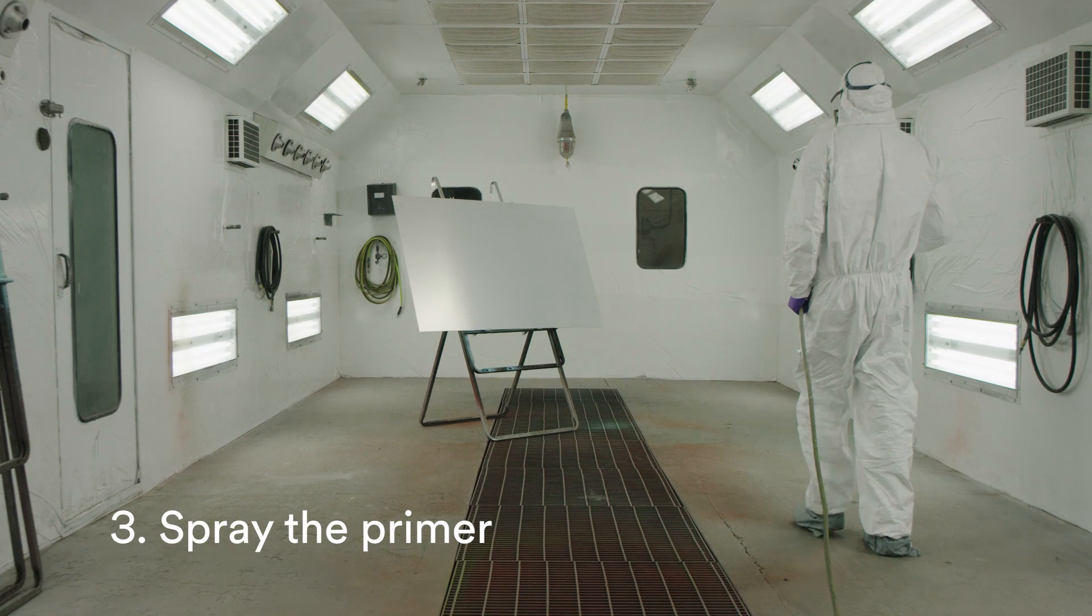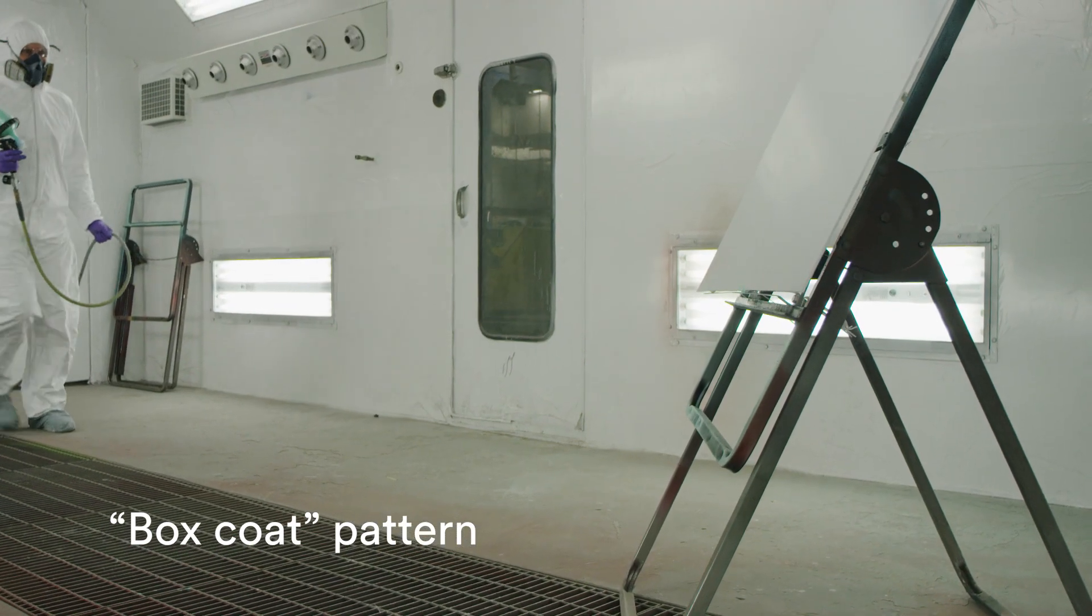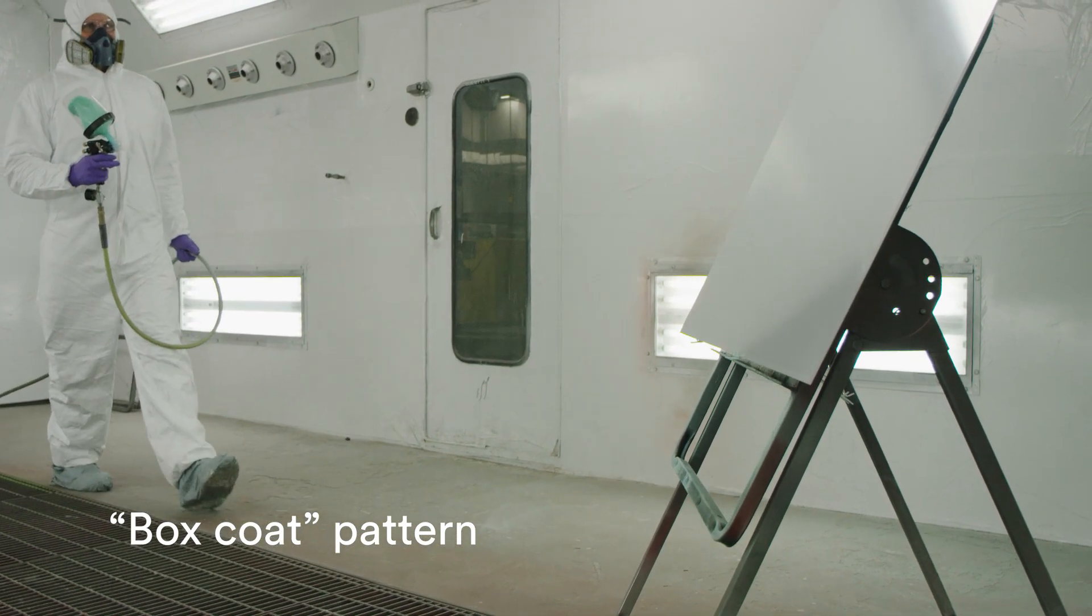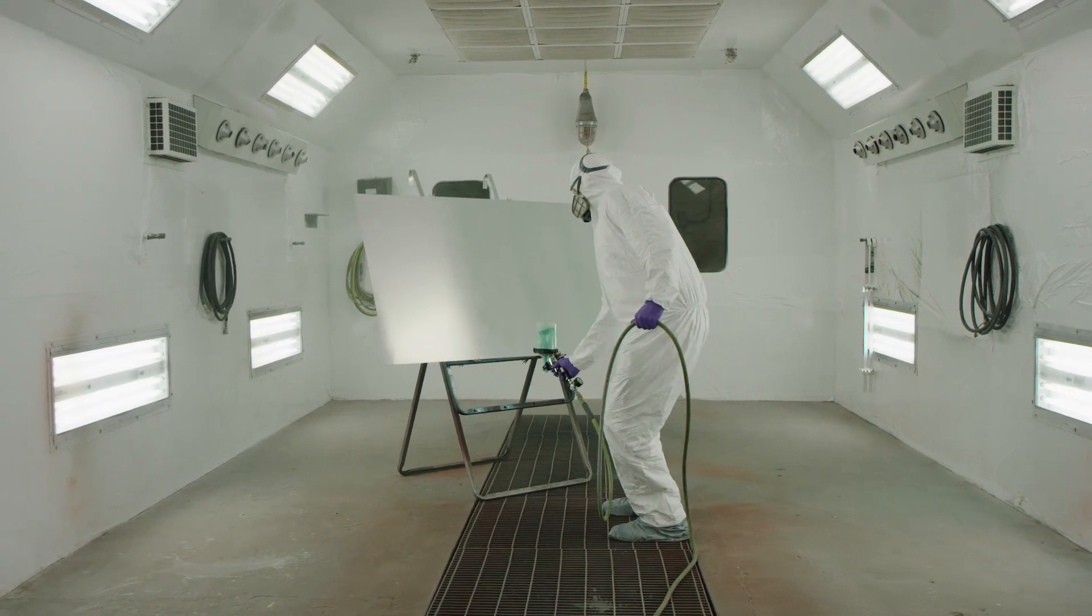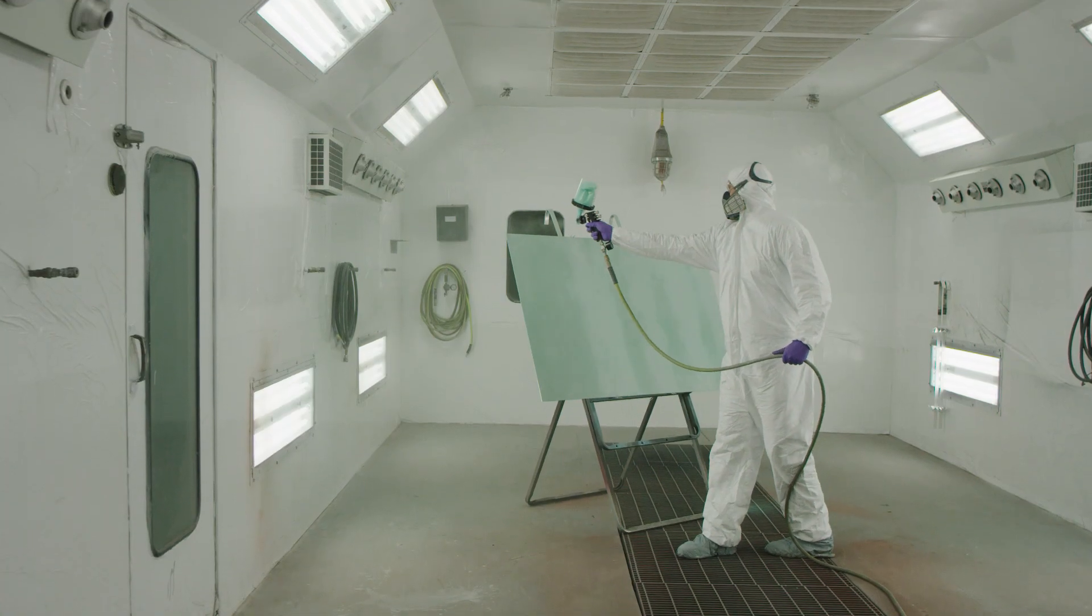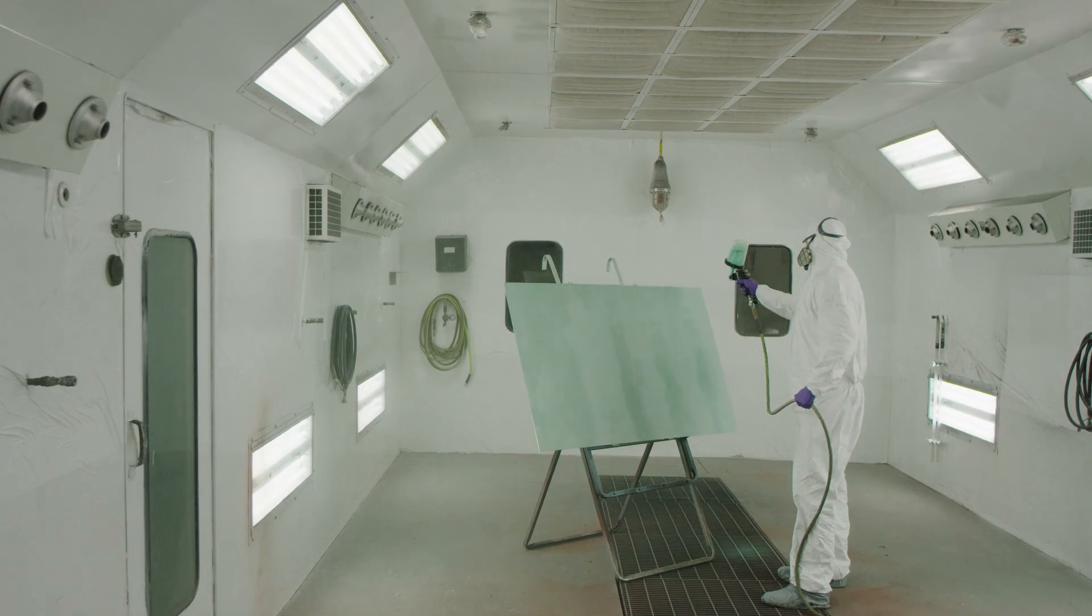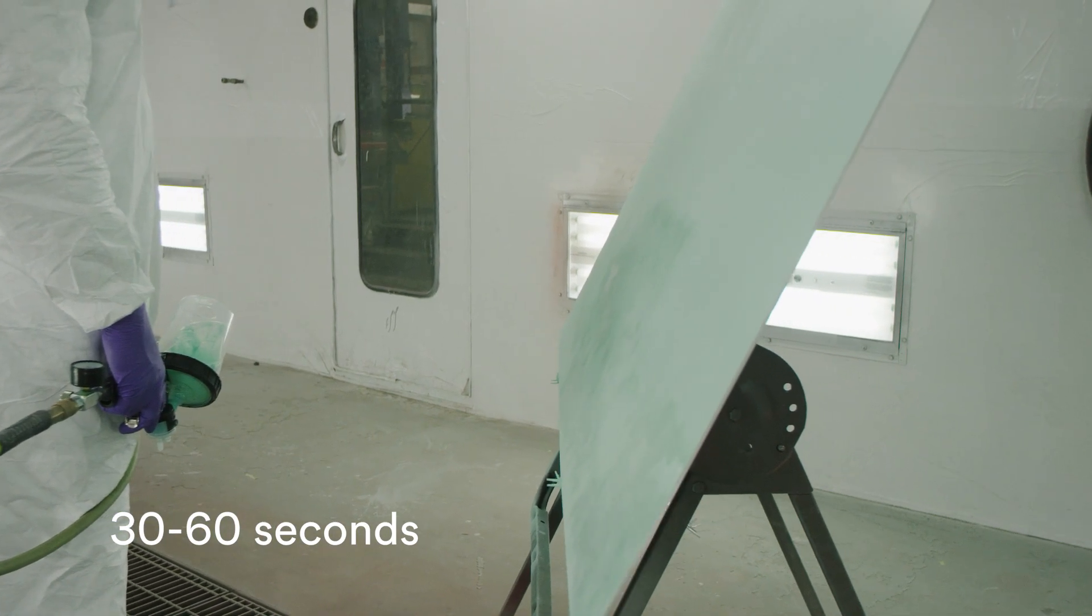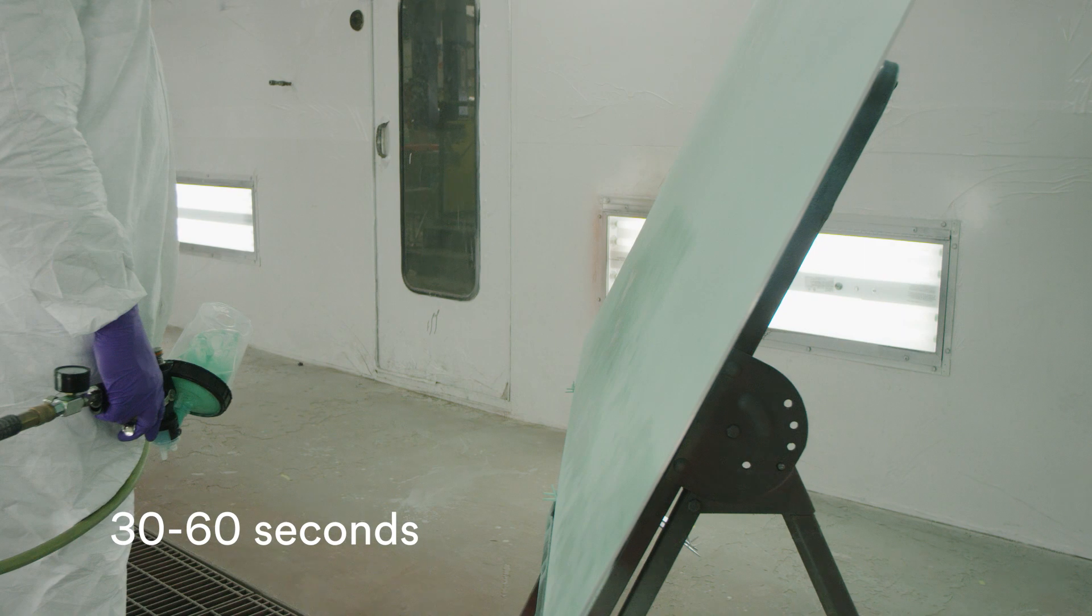Ready to spray? Use a box coat pattern. One box coat has two spray passes that have a gun swing pattern perpendicular to each other. For best post-cure appearance, allow flash-off between passes. It is recommended to allow 30 to 60 seconds between each pass, or until flash-off.